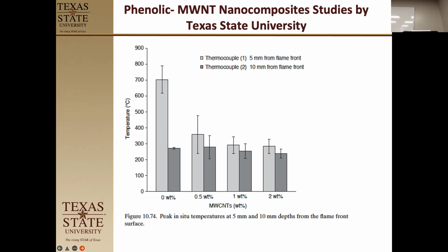They haven't met the threshold to do thermal transfer. They've met the threshold to do electrical transfer, but not thermal transfer. They're not touching enough to get the heat transfer. So they're all acting as isolated little islands. And so if they upped it to 10%, you'd have the percolation threshold for thermal transfer, and you would see them go up. But because they're below that thermal percolation threshold, it doesn't transfer the heat. Remember the one loading that we saw that had that high heat transfer, that was 29% carbon nanofibers. So that has to be high enough to transfer heat. Here at this loading, we don't. They're not high enough to transfer the heat.